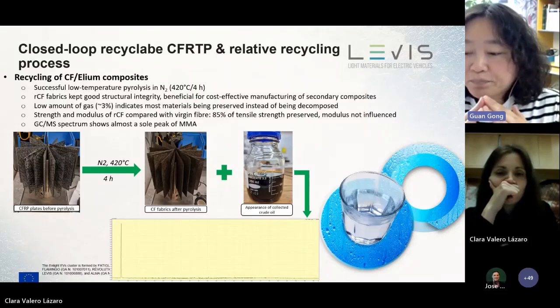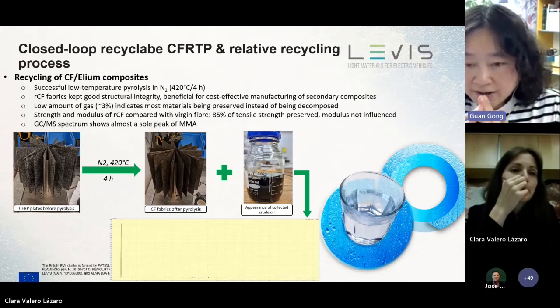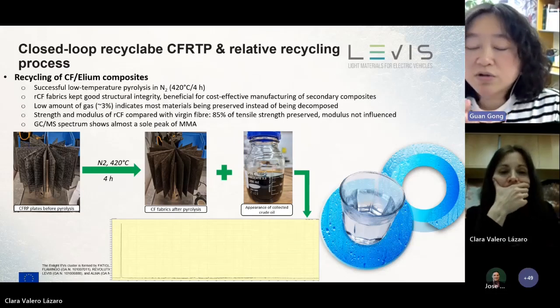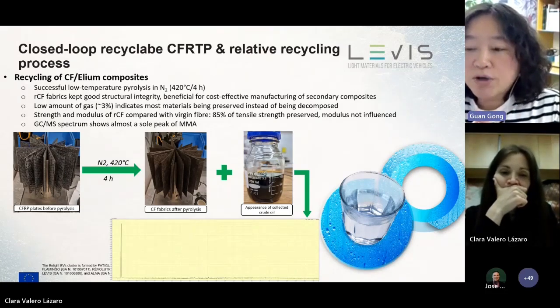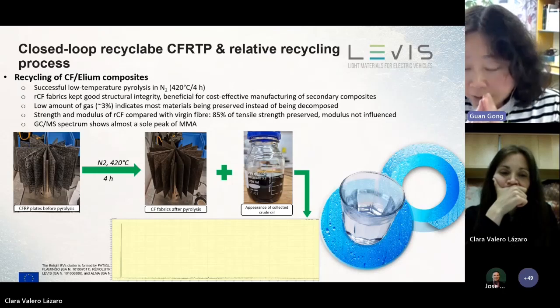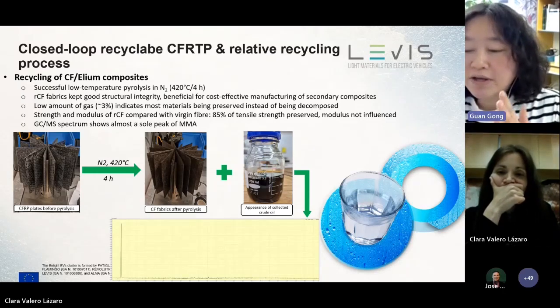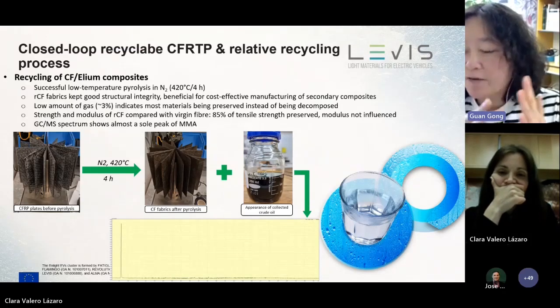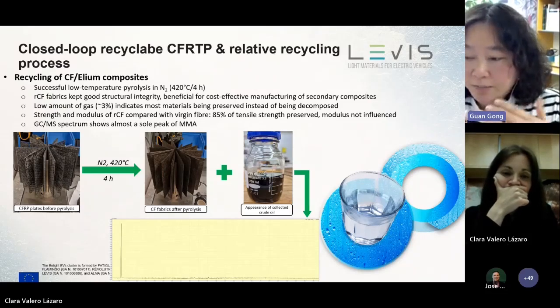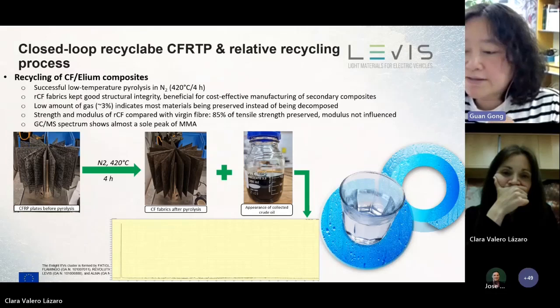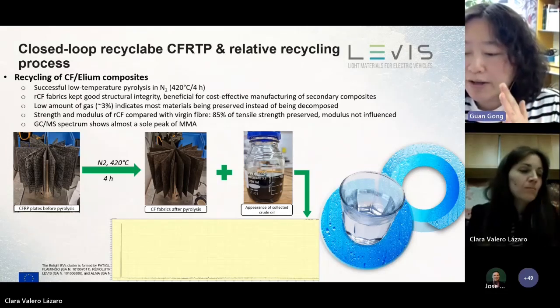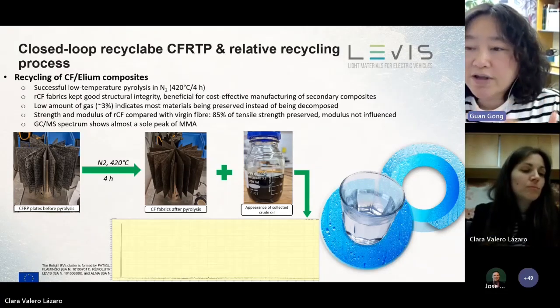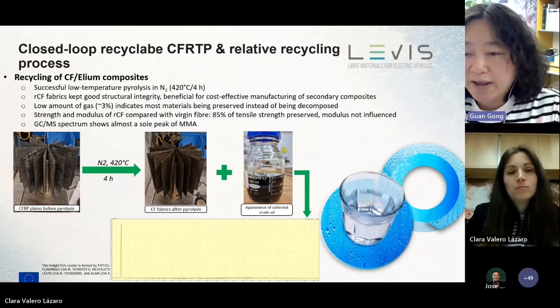And the GCMS spectral analysis done with the crude oil shows a strong peak of MMA, which is the reactive monomer of the acrylic resin. So those results indicate that most materials in the carbon fiber reinforced thermoplastic that is recycled in this project are being preserved instead of decomposed into gas.